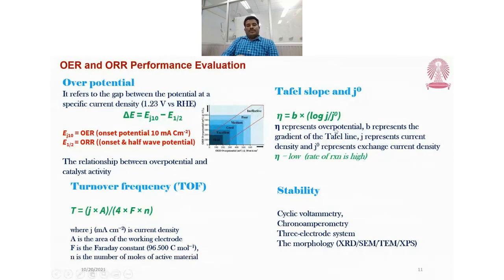We can compare from the slope. The Tafel slope method is an empirical formula: eta equals b times the logarithm of j over j naught. Eta represents the overpotential, b is the gradient of the Tafel line, j is the current density, and j naught represents the exchange current density. When eta is low, your catalyst must be effective.